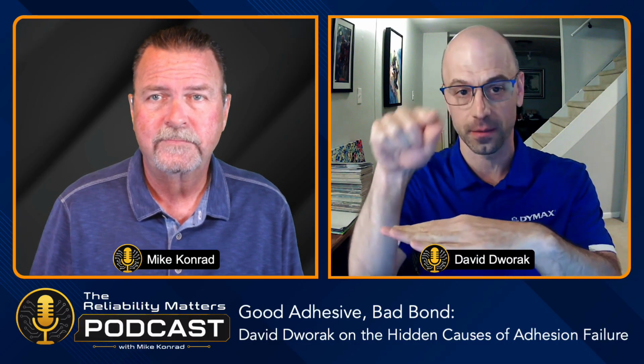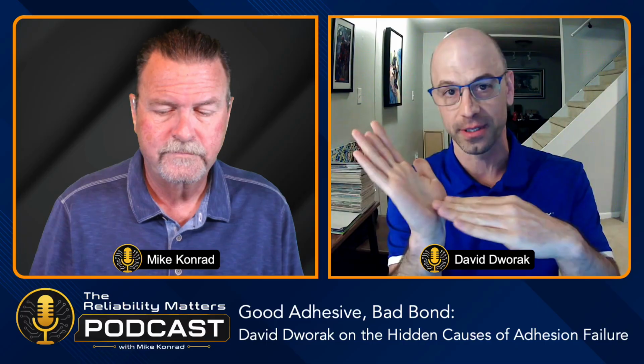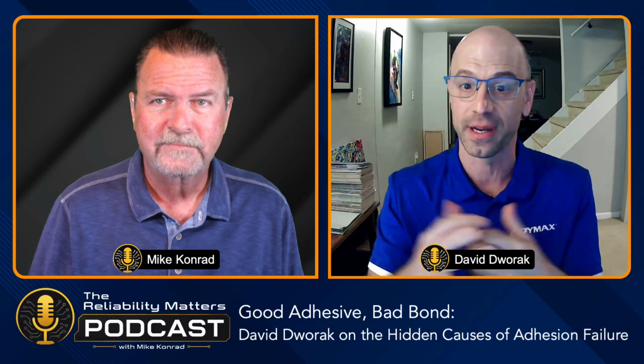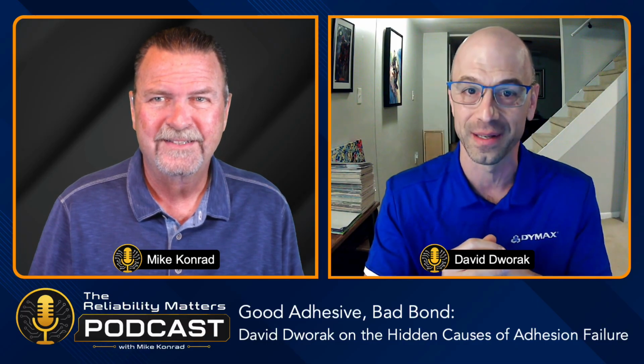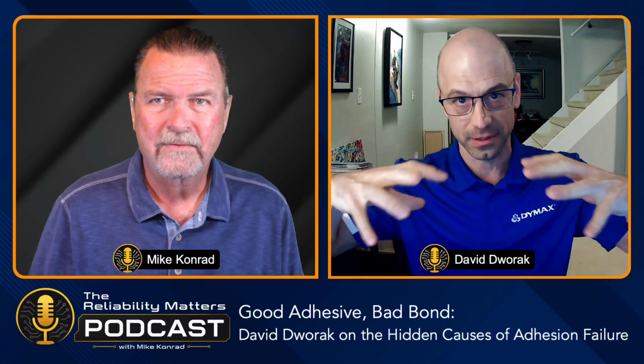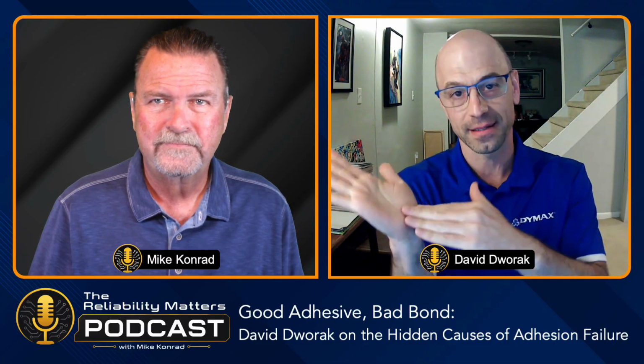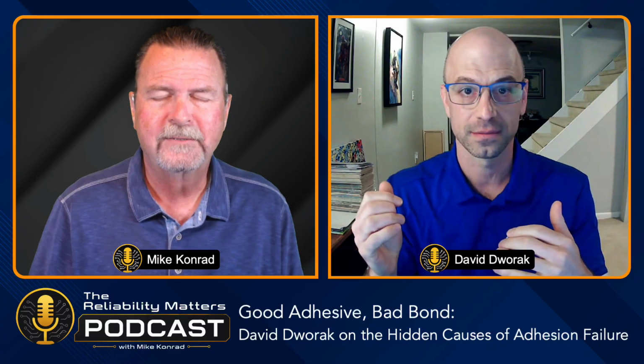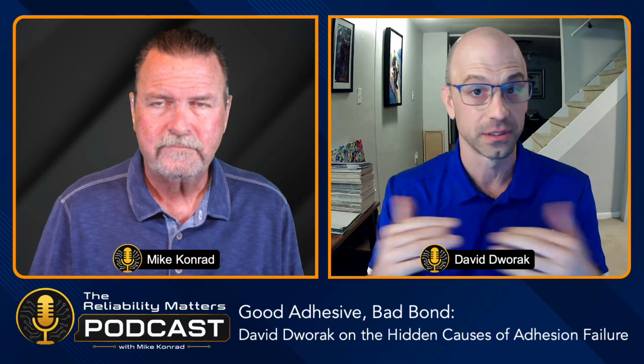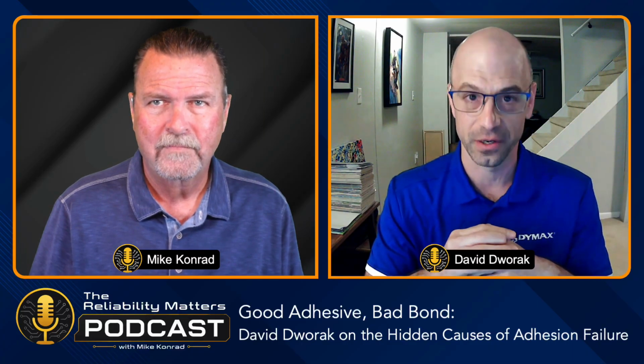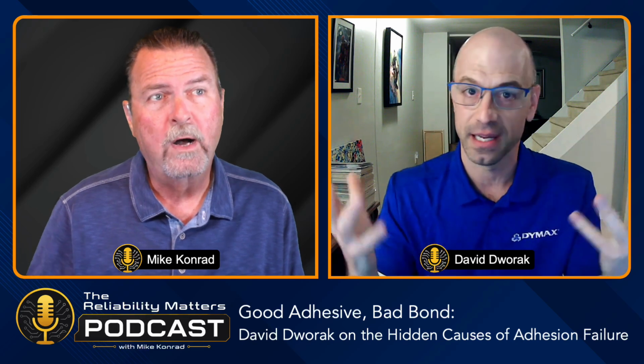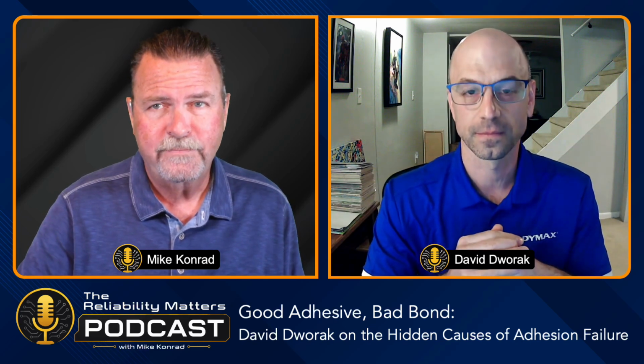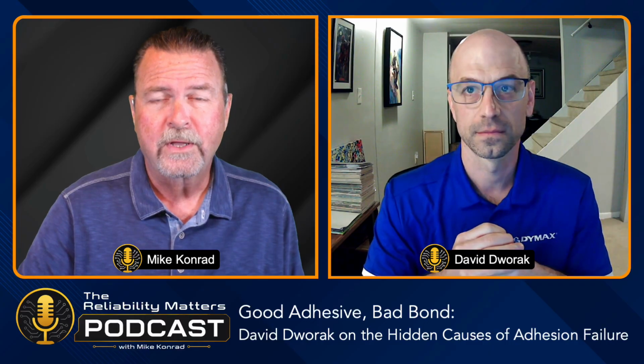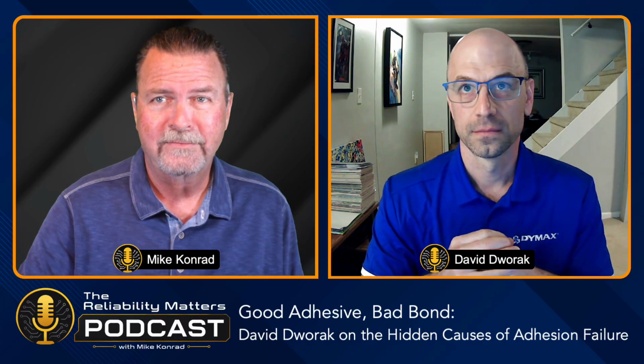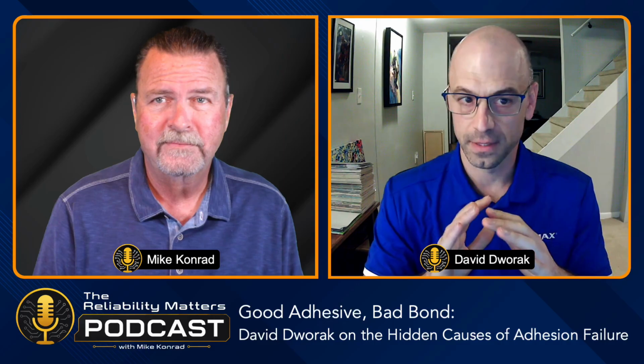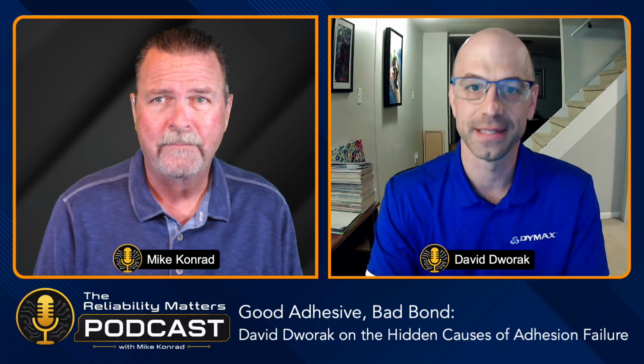And if you've got a water bead and you measure it and it's over 90 degrees, well, that's very hydrophobic and you're going to get poor wetting. And then as that droplet spreads out, that contact angle is going to get lower. Way lower, yeah. So a lower contact angle is good because that's a higher surface energy. And we want high surface energy target surfaces with a low contact angle. That's nirvana. That would be great. Yes, that'd be ideal.